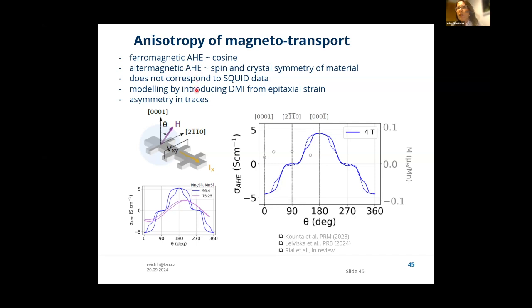And indeed, this is what we observe here. So let me show these data. Here we have certain orientations where the anomalous Hall effect is absent, and then certain regions where suddenly the anomalous Hall effect appears, and it still fulfills this sort of cosine-like symmetry, but with this highly anisotropic character. And here in the gray points, we also show the SQUID data, which are in no way correlated with this anisotropy of the anomalous Hall data.